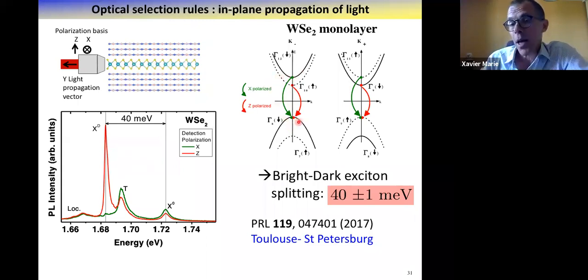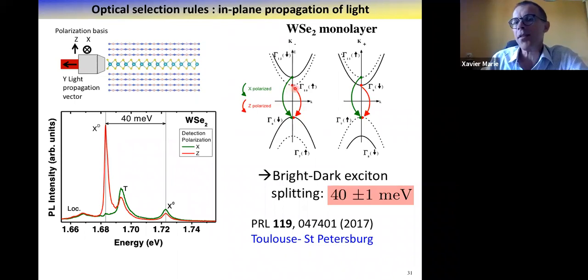But now, if you look at the symmetry of the other transition, the one I called dark previously, it turns out that this transition is allowed not for X polarized light, but it is allowed for Z polarized light, for light where the electric field of the light is perpendicular to the layer. So in order to measure this, what we did is that we performed this experiment collecting the luminescence by the edge, measuring either the light which is X polarized in plane or Z polarized.